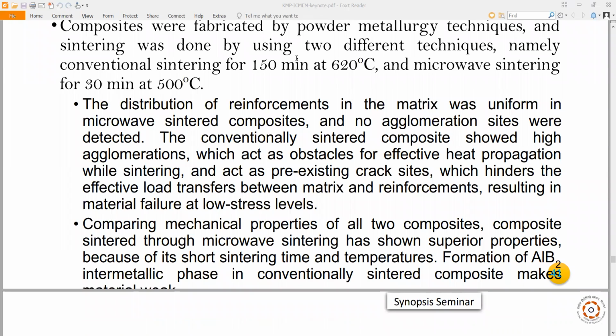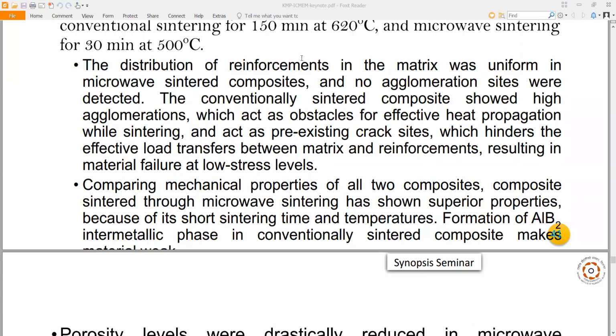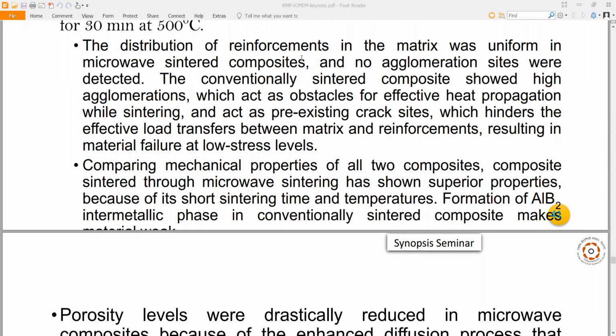Then the distribution of reinforcement in the matrix was uniform in microwave sintered composites and no agglomeration sites were detected. The conventionally sintered composites showed high agglomerations which act as obstacles for effective heat propagation while sintering and act as pre-existing crack sites, which hinder the effective load transfer between matrix and reinforcements, resulting in material failure at low stress levels. Then comparing mechanical properties of the two composites, composite sintered through microwave sintering has shown superior properties because of its short sintering time and temperature. Formation of AlB2 intermetallic phase in conventionally sintered composite makes it weaker.